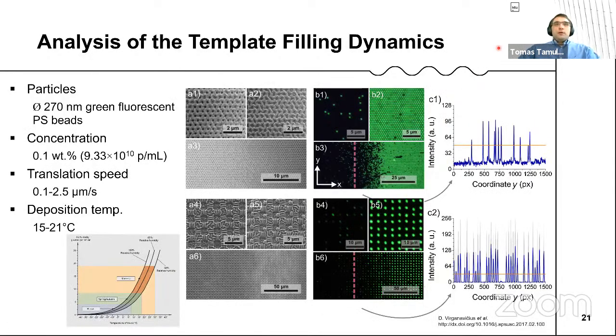So we did some research with polystyrene spheres that are fluorescent because it's easy to see them. And we investigated what happens when we have a trap that fits one particle and a trap that fits many particles, and did those deposits under slightly different conditions. You can play with the speed and with the temperature. Also you have to take into account the humidity in your lab, because you have to control the dew point in your experiments. Then we analyzed those images, taking many lines through the image and analyzing them automatically with some code, and calculated the yield of this deposition.